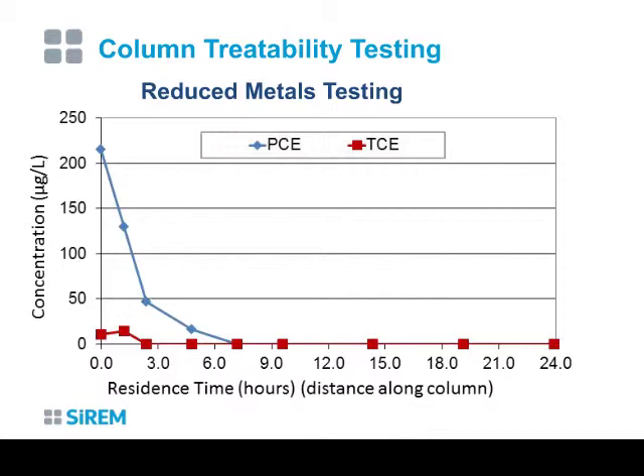And so this is a snapshot at a discrete sampling event from a column study looking at zero-valent iron, where we see a residence time or distance along the column. So if we have 7 sample events over 6 to 8 weeks, at each sampling event we'd get a snapshot just like this, and we'd see different results. In this particular case, we see the PCE and the TCE at the influent, which by about 6 hours of residence time is completely degraded.